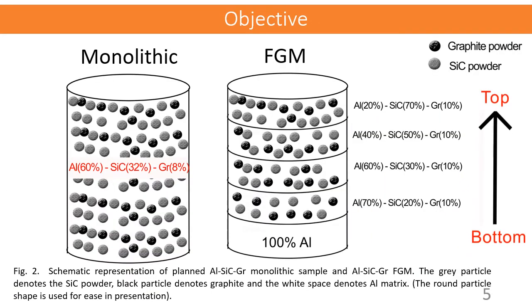One of our prime objectives was to fabricate a functionally graded material. The unique characteristic of FGM is the ability to tailor the material's property depending on the requirement. So the majority of applications require very high surface hardness with good fracture toughness. This is not possible completely in a monolithic sample where the composition is the same. But in FGM we can explore this property, and we thought of fabricating a stepwise gradient FGM where a pure aluminum ductile core is available at the bottom, and as we move from the bottom to the top, the silicon carbide or reinforcement content increases, so we will have a superior hardness.